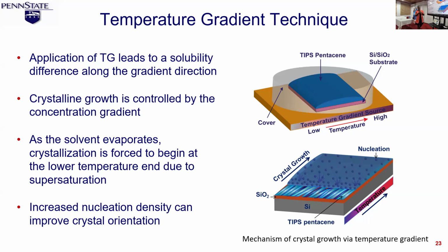So that's the idea behind the temperature gradient method. What we need on the cooler side is called the nucleation site. So we need a bit of those solutes in the solution to create a seed layer for crystallization to happen. And then on the hotter end of it, all the solutes would have dissolved over there. So crystallization starts happening on the cooler side because you have the nucleation site on the cooler side. And as the solvent evaporates, you have crystals forming from one end to the other. And that's how the orientation is gotten.